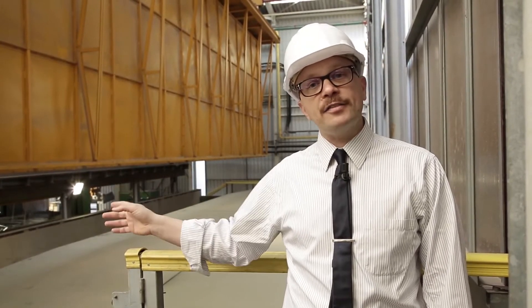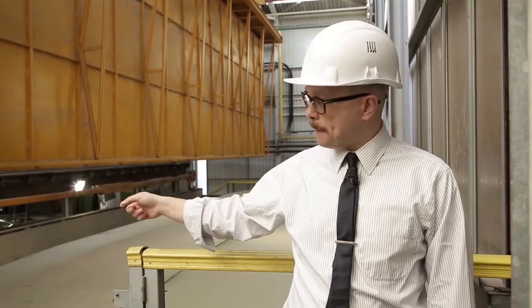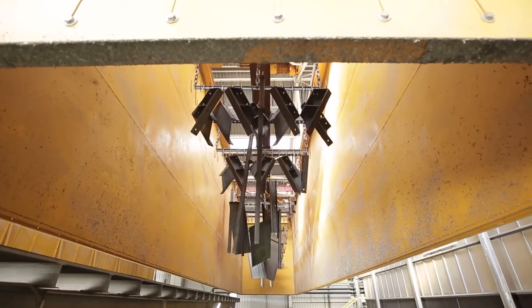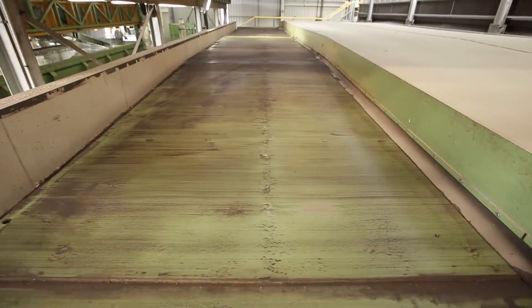What you see here is our standard five-stage drying unit. The drying tunnel connects the pre-treatment tunnel behind me and the galvanizing kettle far on the right. Racks are entering the drying tunnel from inside the pre-treatment enclosure, which allows not to disperse any fumes in the environment. Racks are then advanced all the way down to the last station, where the galvanizing crane goes down automatically and picks up the rack to go into the galvanizing stages. By using a five-step drying unit, this allows single pieces of steel to remain nice and dry before they enter the galvanization step, avoiding splashes and warpage.